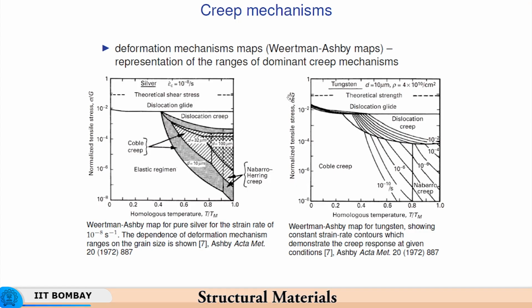So, this is sigma by G. G in case of tungsten is very high, and therefore sigma by G is close to 10 to the power minus 7. So, even at that you have very high creep resistance, meaning lower rate of creep. Here dislocation creep happens again, like in case of silver, and at 10 microns grain size, which is a very fine grain size, the creep happens at a relatively lower stress. As you see here, close to 10 to the power minus 7 is the stress at which the creep takes place.